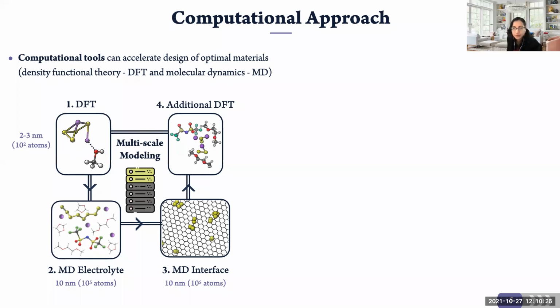We start from the database of the individual electrolyte components like the solvent, salt, additive, and we perform density functional theory calculations for these components in order to screen or down select potential candidates based on performance metrics like the electrochemical stability or chemical stability of these components, and these are relevant properties for the battery performance overall.